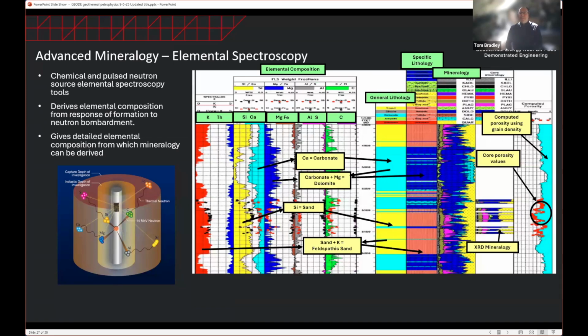So that's a basic way, but let's say we want more detailed mineralogy. This way we can look at measurements such as elemental spectroscopy. And there's both chemical source and pulse neutron source that tells us this. And the way these work, by basically emitting high energy neutrons into the formation and measuring the gamma rays that come back, the spectra of the gamma rays, we can start to derive the elemental composition of the formation in terms of potassium content, thorium content, silicon content, calcium content, magnesium, iron, aluminium, silicon, and carbon.